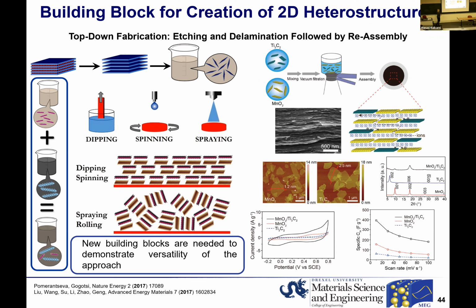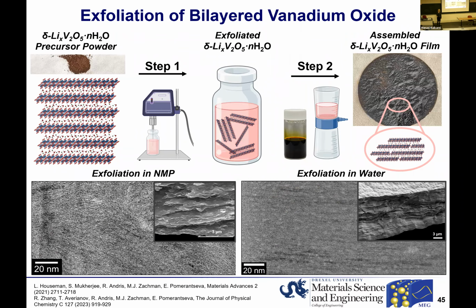Again, this is a very common method where two dissimilar materials are exfoliated to form suspensions of two-dimensional nanoflakes. Then they get mixed, and various processing approaches such as spin coating, spray coating, or simple vacuum filtration can be used to create a heterostructure film. This has been shown, for example, for manganese oxide and titanium carbide nanoflakes. But the issue is that no one has ever exfoliated bilayered vanadium oxide. So again, inspired by the work on MXenes by our laboratory neighbors and Professor Gogotsi's group, we just used simple ultrasonication and powder of the lithium pre-intercalated bilayered vanadium oxide.